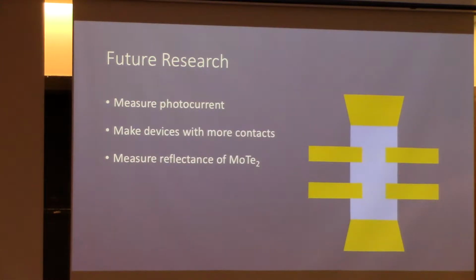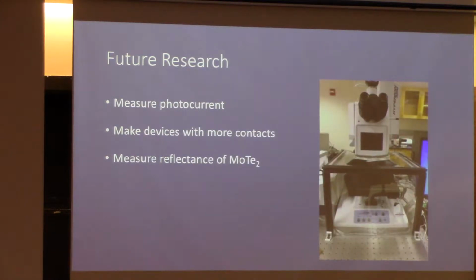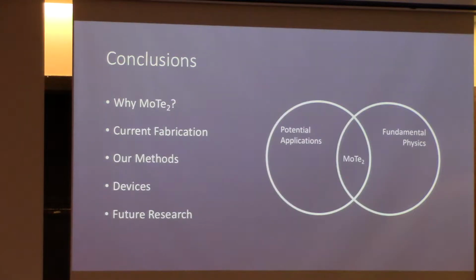I also hope to make devices with more contacts, because basically the more contacts you have on your flake, the less impact the resistance of the contact material has on your measurements. So making more contacts would enable us to get even better photocurrent measurements. And finally, I'd also like to measure the reflectance of my sample in this mid-IR microscope, and my colleague Bailey is about to explain why reflectance data is so important for these measurements, so I'm going to leave that explanation up to her. So in conclusion,